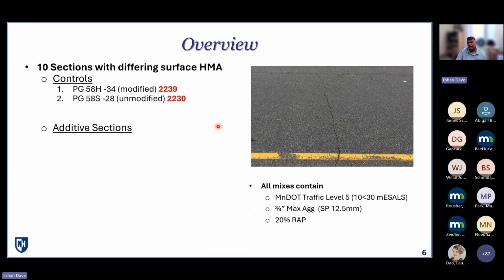So the first two are really controls, and there we are primarily comparing our standard unmodified asphalt binder versus modified binder, or if you speak the MnROAD lingo, then that would be your B oil versus C oil. So it's essentially comparing cell 20 to 30, which is this mix 2, which has your unmodified binder, and then cell 20 to 39, which has modified binder.